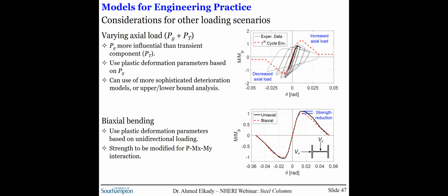For biaxial bending, again, with respect to the cyclic envelope, there is no significant difference when it comes to the plastic rotation parameters. The only thing that you will need to consider is the reduction in strength to account for the PM interaction, which you can actually do using the code's equation.